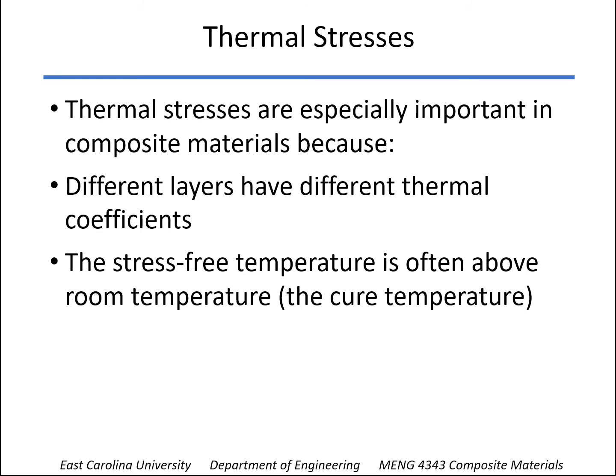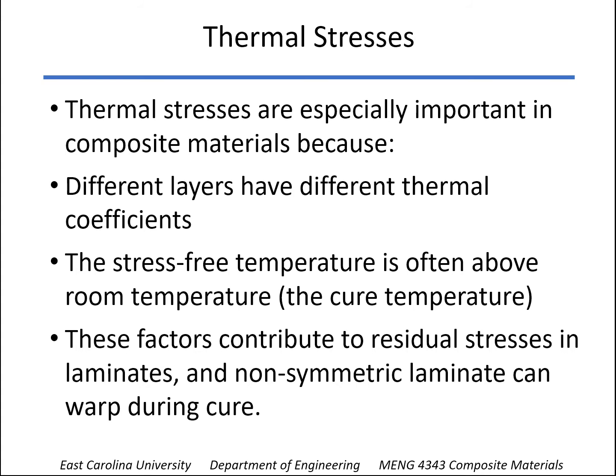Then once the cross-linking of the resin begins, you've really locked in the orientation at that point, so we call that the stress-free temperature. And when you come back down to room temperature, then you're going to have some stresses that get built in, and those residual stresses can actually be kind of high. Also, if you don't have a symmetric laminate and you do this curing, if you go in with a flat laminate, put it in the oven, and it's not symmetric, when it comes out of the oven, it's going to be bent.